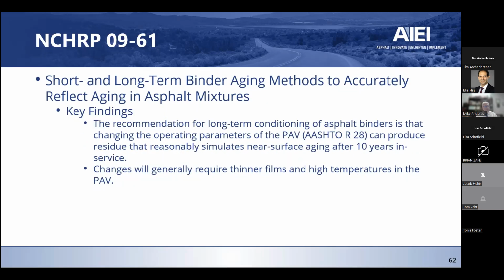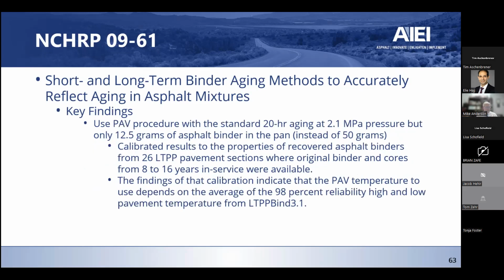Oops, I went backwards, sorry. What they found from the PAV is that you can change the operating parameters of the PAV to reasonably simulate near surface aging after 10 years in service. But to do that, it's going to require thinner films and potentially higher temperatures. So in their research they looked at how to model that, and that was 20-hour aging at 2.1 megapascals, which is the standard pressure, but only using 12.5 grams instead of 50 grams. In essence, you've cut the film thickness in that pan from 3.1 millimeters down to 0.8 millimeters. So it's a much thinner film, and it allows oxygen to diffuse quicker into the asphalt film itself.